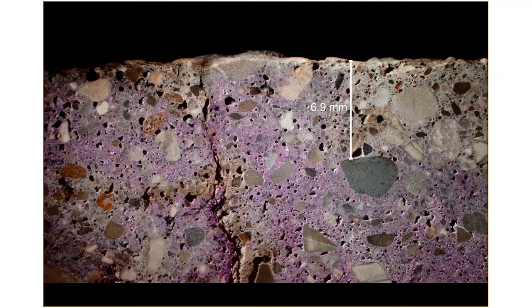We have this anomaly where we have produced concrete that has some air entrainment in it, and we'll touch on that a little bit later, but there's some speculation that some oils or some animal fats or tallow got into the production of this Portland cement just as a grinding aid, and this material ended up here, and it ended up as a surfactant, and it produced a lot of little bubbles. Now that's speculation. There is some history with that, not related to this project per se, but we've got little bubbles, and this concrete was placed 128 years ago. And so very interesting to see this, and another factor on why this concrete survived.